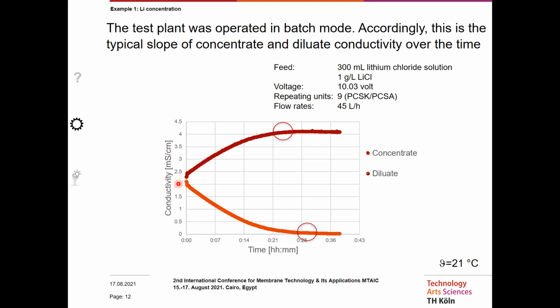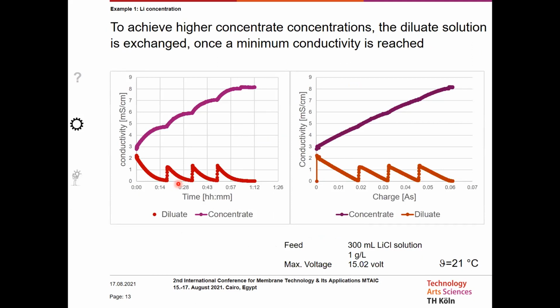So if we want to increase the concentration of the concentrate much further, then we would leave the concentrate solution inside the tank and use a new dilute solution from which the ions are transported into the concentrate. And this is shown here on the next slide. On the left hand, you can see the conductivity over the time. And you see every time when we change the respective dilute chambers, the dilute solutions, then the concentration of the dilute is rising. And again, during the process, the conductivity is falling because of the transport of the ions into the concentrate. And same is here to be seen when the change of the dilute takes place, then the concentration of the concentrate again starts to rise.